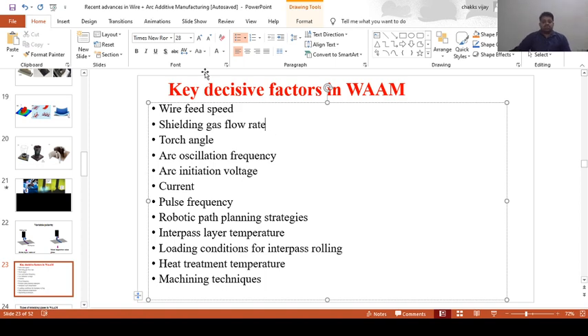Then the next important thing is the arc oscillation frequency. Already I have talked about the weaving motion. At what frequency is this weaving motion supposed to happen? This weaving motion causes a weld pool stirring effect. So that's why this arc oscillation frequency is one of the concerned parameters. Generally we go for 5 Hz, 6 Hz, 8 or even 10 Hz.